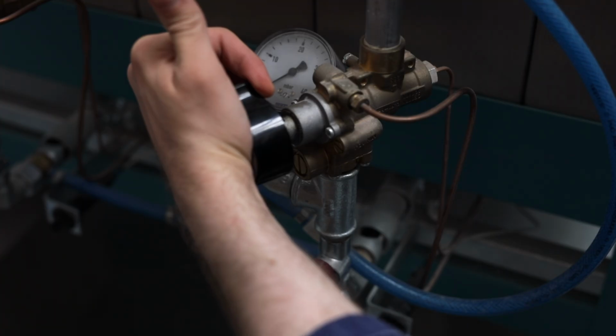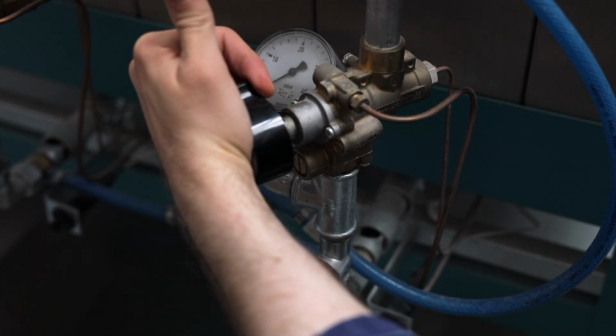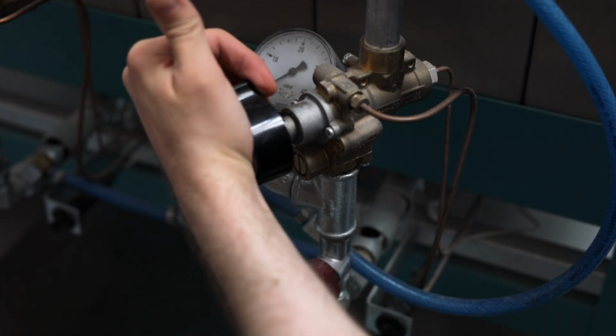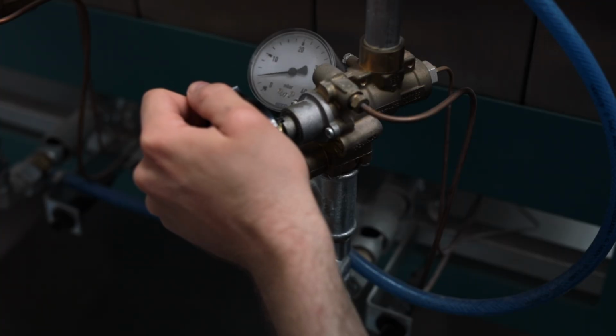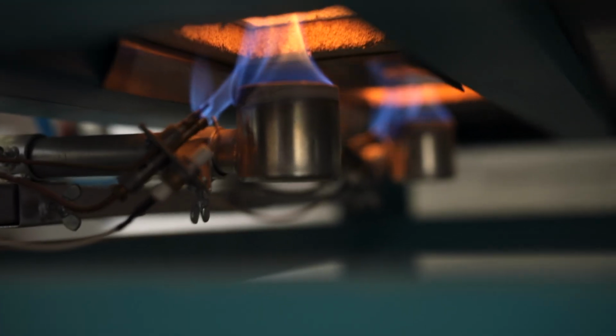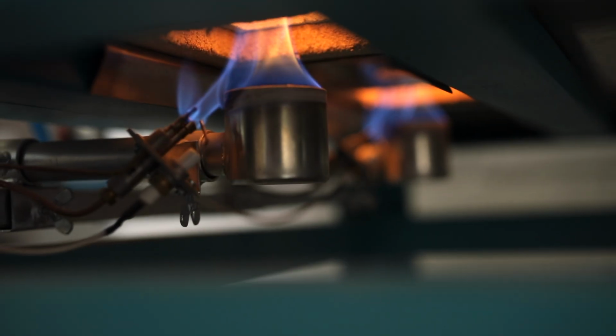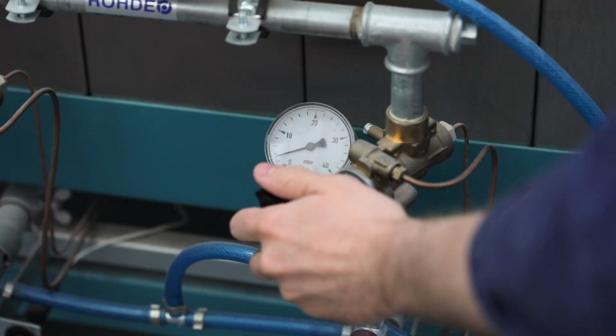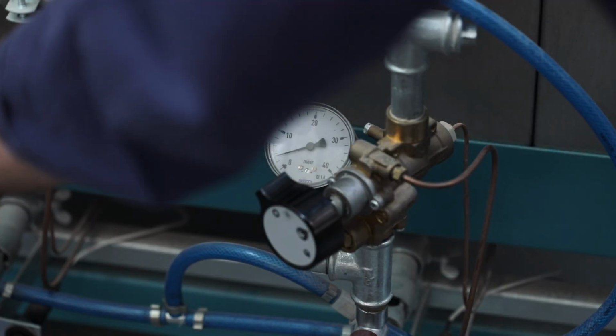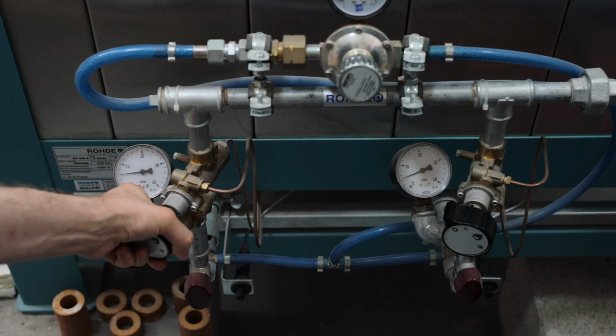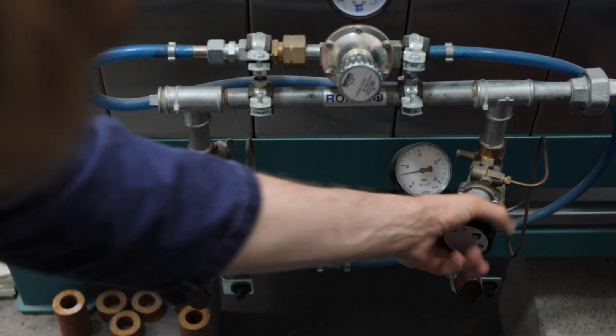I light each of the 4 burners that fire into the bottom of the kiln. I begin the firing by going quite slowly, gradually easing up the temperature to get rid of any moisture that could be left in the glaze, as if a pot is still quite soaked with water and I increase the temperature too dramatically, the pots can quite literally explode. Every 30 minutes I check the temperature and I increase it just a touch, and at a certain point I turn on an air compressor which helps pressurize the flames.